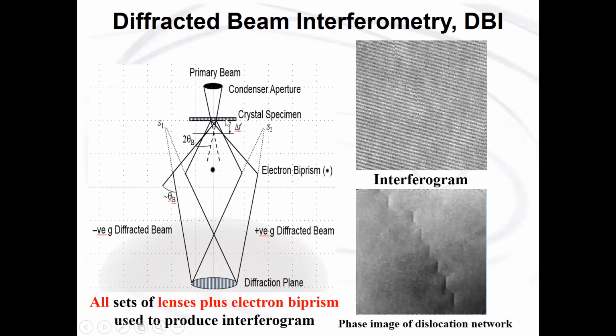diffraction where it occurs within the specimen, and we can produce a change in focus, which then allows the diffracted beams to separate sufficiently so that they don't interfere with a biprism used to deflect the two beams to an observation plane, such as the diffraction plane.